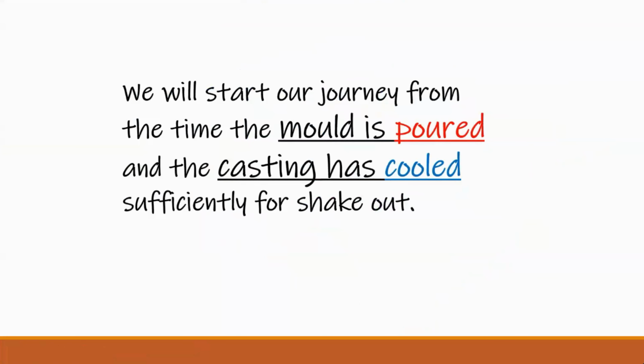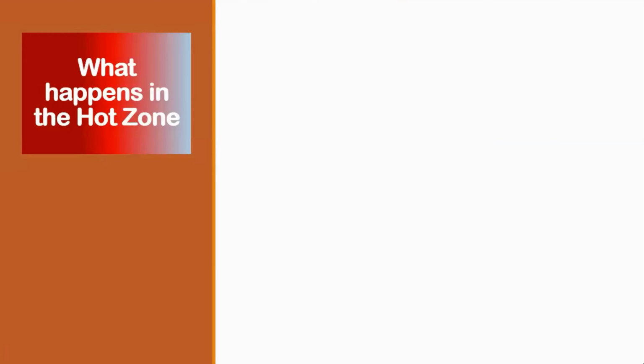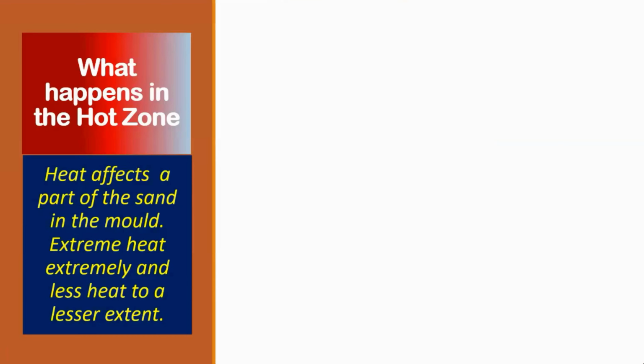So we start our journey from the time the mold is poured and the casting is cooled sufficiently for shakeout. That means the casting has come out and then it has shaken out all the hot sand out of it. So that's where we start with the sand, the hot sand. What happens in the hot zone? Heat affects a part of the sand in the mold. Extreme heat extremely and less heat to a lesser extent.